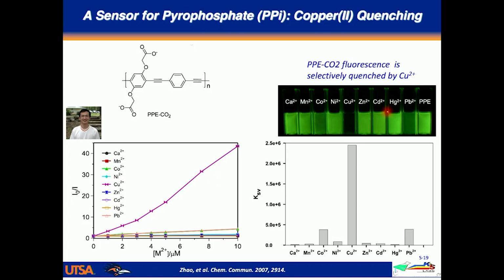If you measure the Stern-Volmer slopes, they're shown here. So these are the Stern-Volmers. That's copper. The Stern-Volmer is around 2 times 10 to the 6th, so it's a pretty efficient quencher. It turns out all the others still give some quenching, but compared to copper, they're much less efficient. So the question that we ask first is, why is copper so efficient?